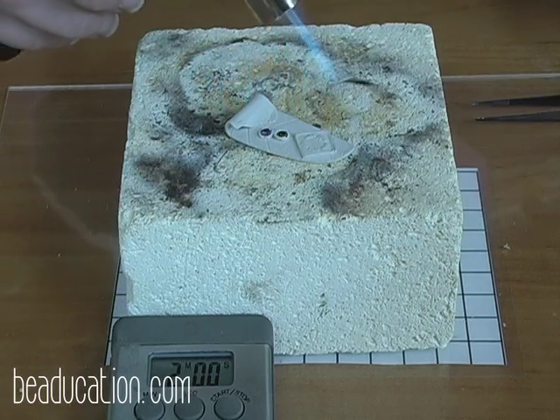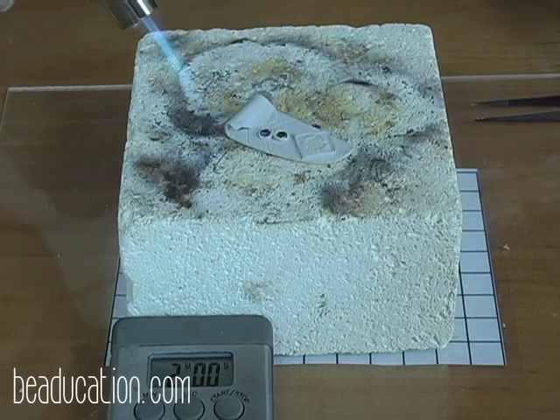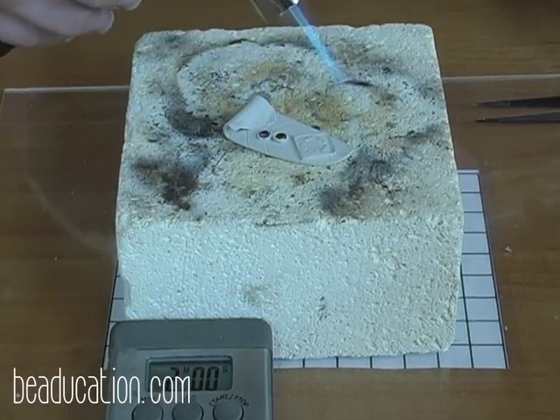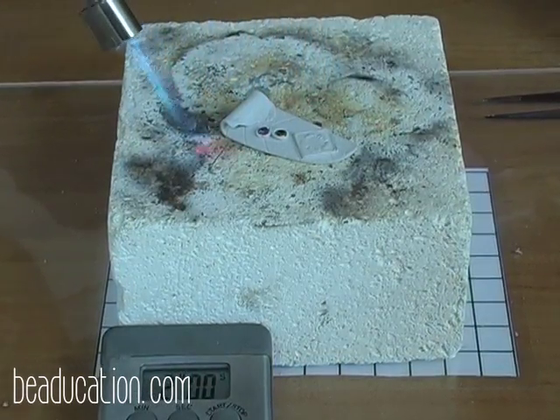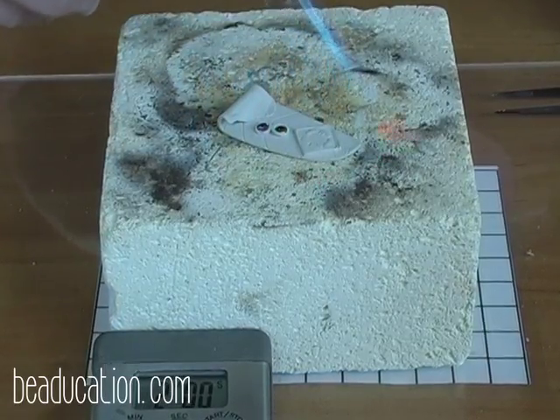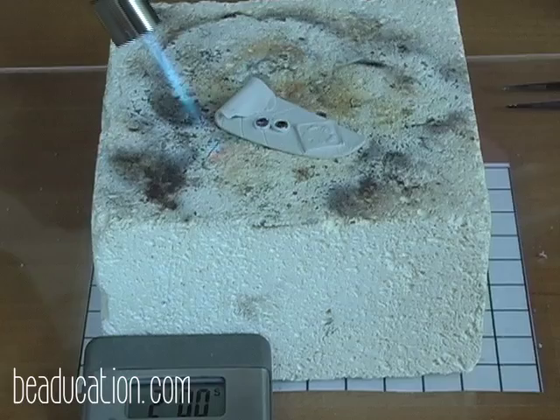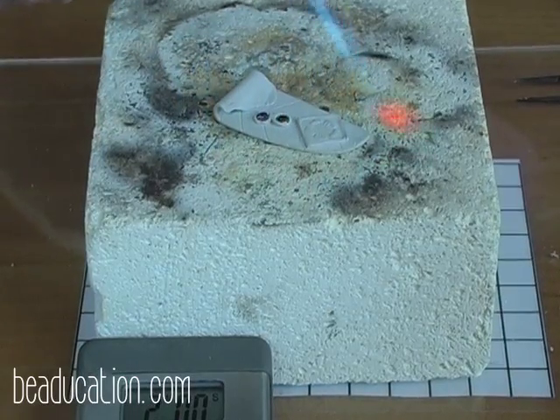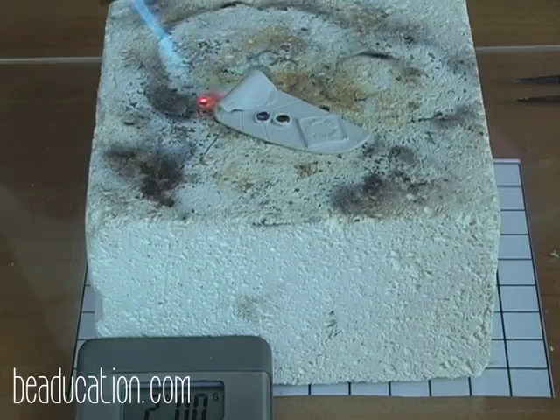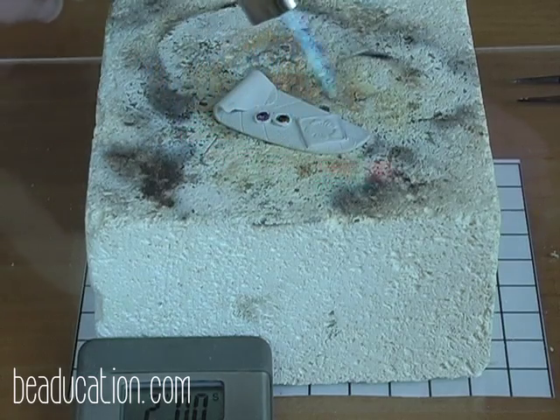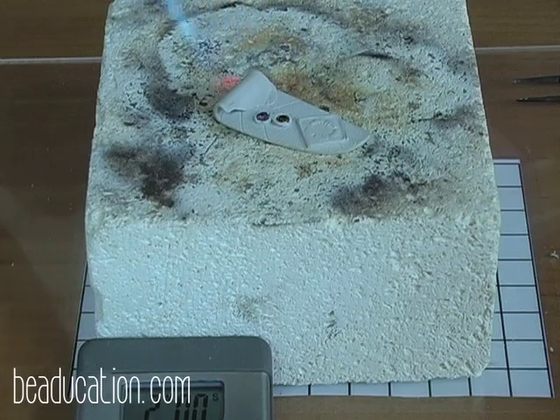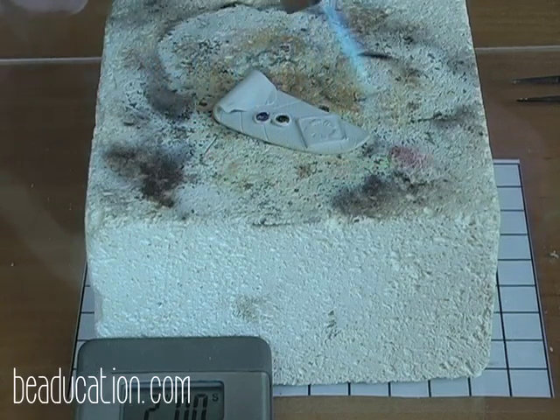Now, you really want to make sure that your piece has completely dried, because if your piece is not completely dry and you start to heat it up, the moisture is going to want to escape somehow, and usually it'll escape through a little eruption in your clay. So please make sure before we start to fire that your pieces are dry.